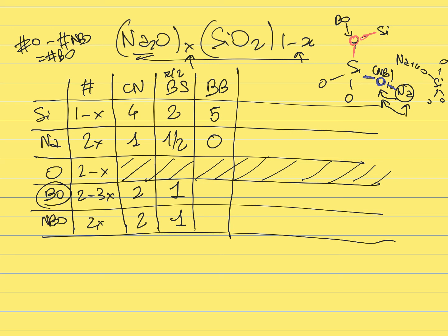So now the glass transition temperature of sodium silicate glasses is going to be much lower than that of pure silica, which means that the bond bending constraint between the silicon, oxygen, and silicon angle should be counted just like any other constraint, because now this type of glass is formed at lower temperature. Those constraints are now active because the temperature is not high enough to break them. So now I should put 1 because these constraints should be counted.